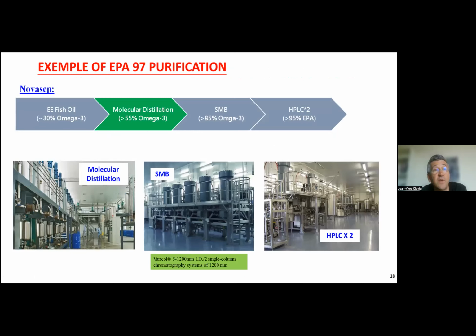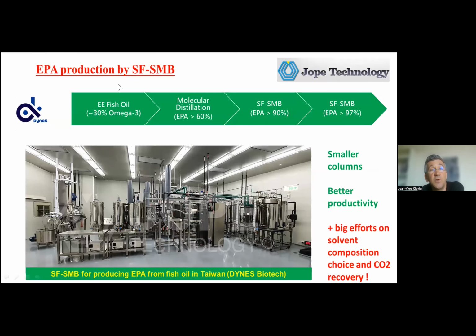So going back to the example of EPA purification, when we developed the EPA purification at above 99%, CO2 was not chosen because it was not economical, it was considered not the best solvent. And the process was developed in the 90s, first with molecular distillation and then supercritical fluid fractionation, and then using liquid SMB and batch chromatography to purify these omega-3 ethyl esters. So a very big column was built in the south of France for this application. And recently, the supercritical fluid simulated moving bed has finally been developed.